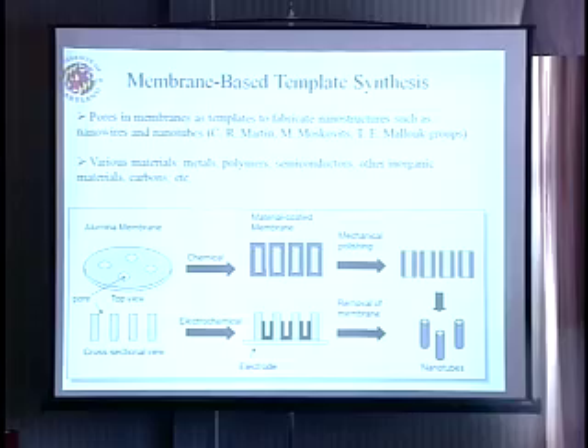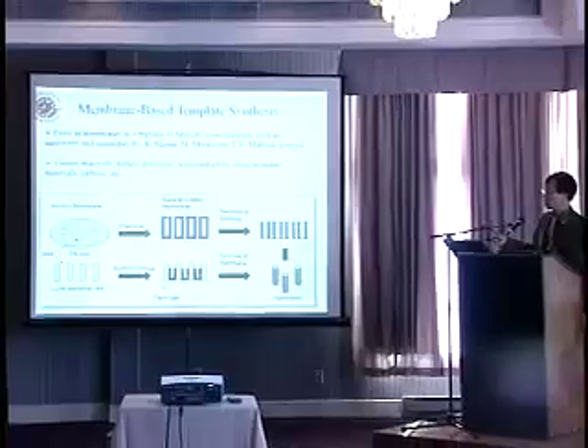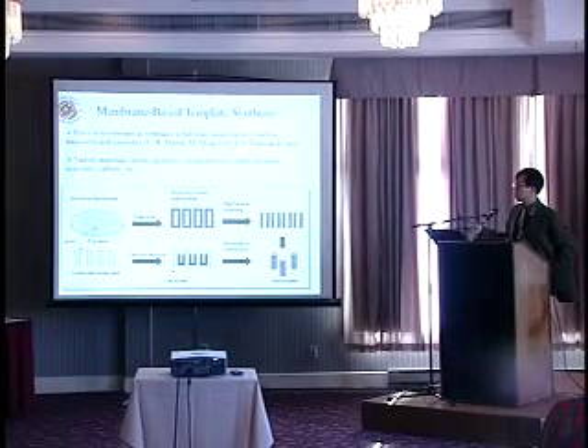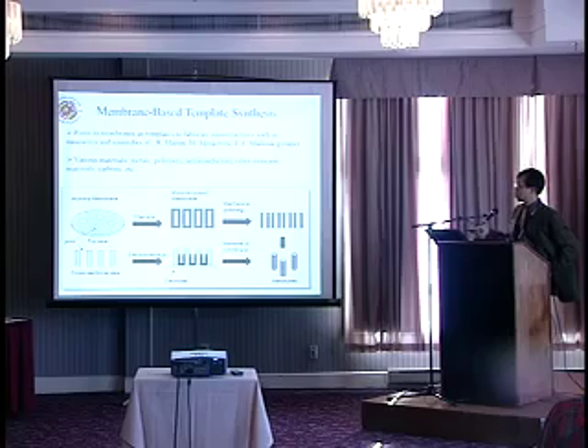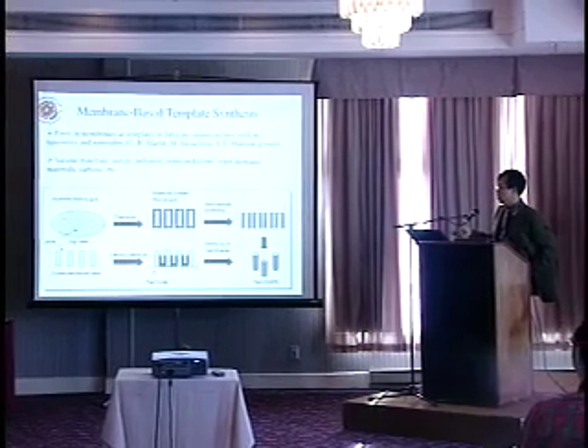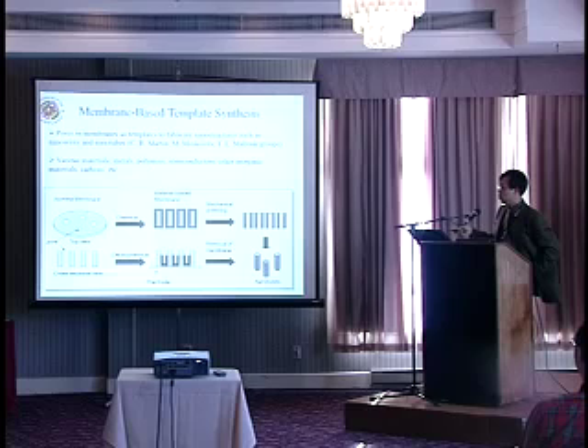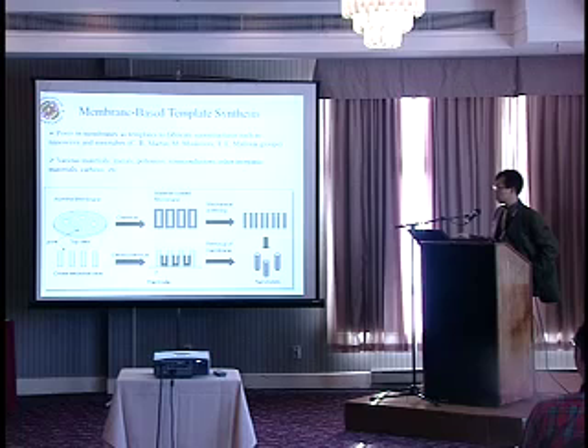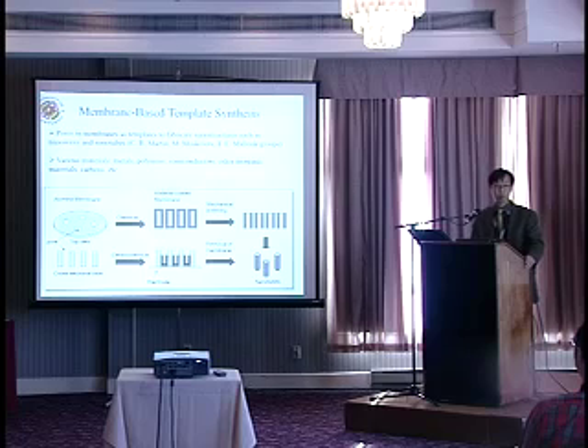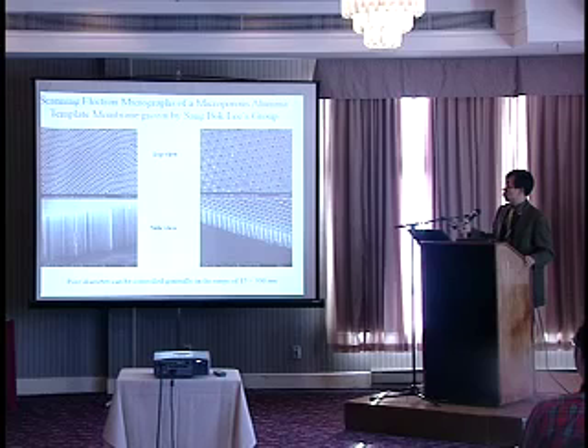So you take this porous membrane and dip it into an interesting solution, take it out, dry it, then you will see all those materials coated on this membrane, including the inner pore surfaces here. And then we remove the top and bottom layer. Then if you can selectively dissolve out the template, you can have this nanotube structure here. Also, certainly there is an alternative route to grow this nanotube structure using some other electrochemical technique or other deposition technique. And now this is one example of a porous alumina membrane.